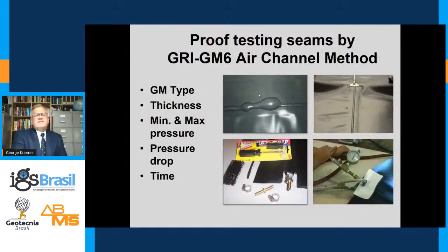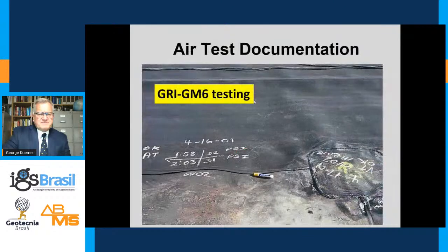As far as the test is concerned, the criteria is set forth with GRI GM6 for air channel testing, the specification. The specifications are based on geomembrane type, thickness, minimum and maximum pressures that are associated with those types and thicknesses, and a pressure drop over a given time. And all of this is called out in the standard. What you don't want to see are these aneurysms in the air channel test. This indicates poor seaming, and certainly is what the QA is after.